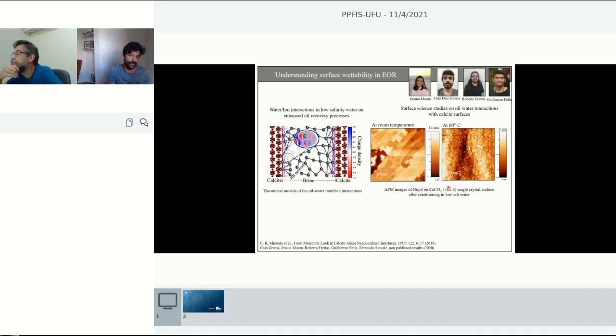So this is, again, a very well-defined surface with a surface plane. And then we look here at how the molecules of oil, these organic molecules, interact in different temperatures and different pH conditions, and then try to judge which kind of interaction is going on to correlate with, for instance, this kind of theoretical models over here.